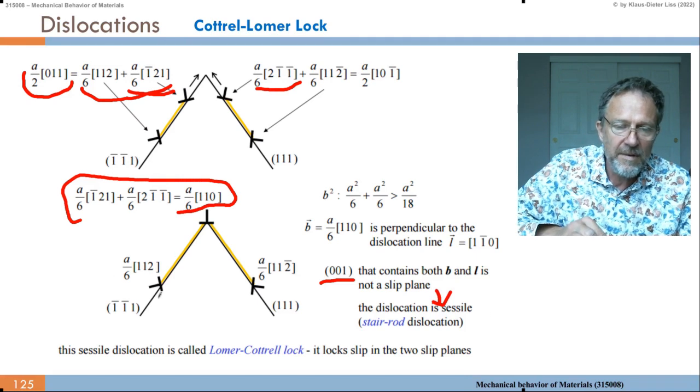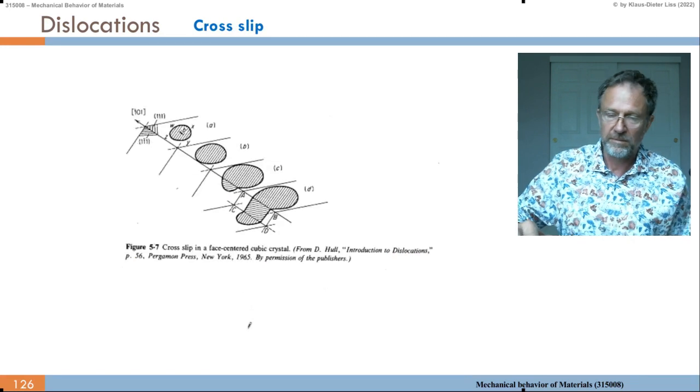So then we have the situation of these stacking faults going onto two planes, going around the corner, with the sessile dislocation here. It cannot move. This one can move, but if this moves, then you change the energy. So you probably want to sit at the typical equilibrium distance here, so this does not move far away, and the same for this one on that side; it doesn't move.